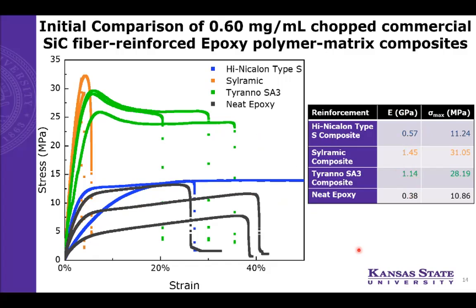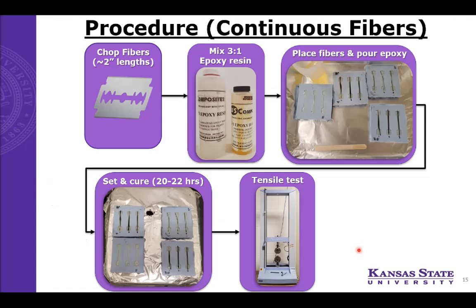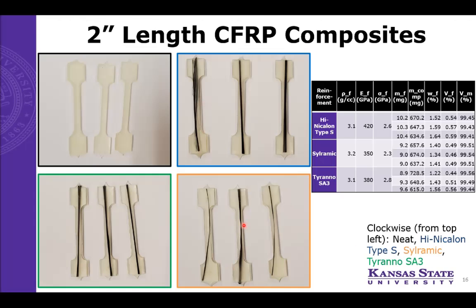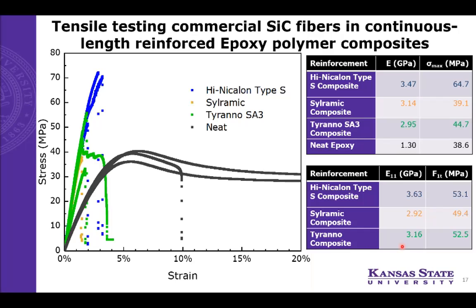So we moved on to continuous fiber testing, which had fewer steps and fewer opportunities for inconsistencies during testing. We chopped the fiber bundles to 2-inch lengths before mixing, and we mixed our epoxy resin and then placed the fibers along the gauge length before pouring that resin, setting and curing, and then tensile testing again. So here we can see what those composites look like post-curing, and we can see they each had roughly 0.5% volume fraction. Using that, we were able to calculate a theoretical longitudinal elastic modulus, as well as a theoretical maximum tensile strength.